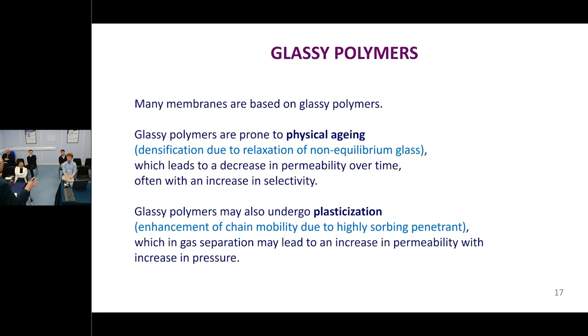But thermodynamics says we want to get rid of internal space. We want to get rid of internal surface. So thermodynamics over time does everything it can to squeeze out all of the space that we're trying to put in. And so you have this process of very slow changes over time, which leads to a densification of the glassy structure. And that leads to reductions in permeability, often with increase in selectivity, though unfortunately not always.